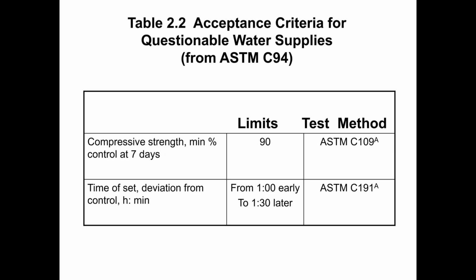All right, so these two tests on compressive strength and set time are just to kind of open the door to the water sample. If it can't pass either of these two tests, then it shouldn't be used. If it can pass these two tests, then there are some chemical analyses that we need to do just to make sure that there aren't any chlorides in it, that there aren't any other deleterious substances that would potentially adversely affect its performance in concrete. But generally, if it doesn't adversely affect strength or set time, that's a good indication that the water is probably going to be okay for use.